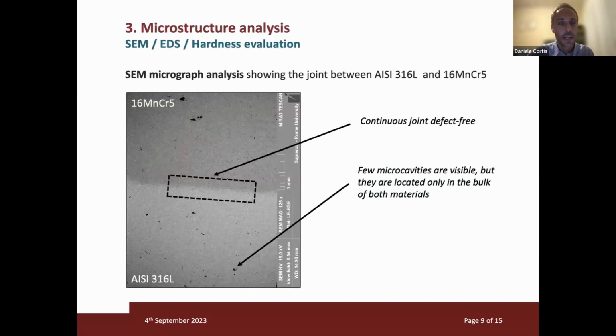Okay, here is the first important picture, the SEM micrograph analysis, which shows that between the two steels there is no defect. So we can state that the junction is continuous and defect-free. This is very important, for example, for the mechanical properties and the thermal conduction. Of course, there are some porosity and microcavities in the bulk of the material that, as you know, is one of the main issues of this kind of technology.